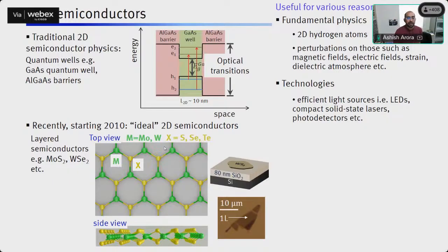When you combine them and create compounds, the compounds are called MoS2, molybdenum disulfide, tungsten disulfide, molybdenum diselenide, tungsten diselenide, and so on. All these combinations can create these two-dimensional layered materials, where you can remove layers one by one and place them on a substrate, such as the silicon substrate shown here. Of course, a very thin layer of silicon dioxide is coated on the substrate because this thin layer makes us see this very thin film.